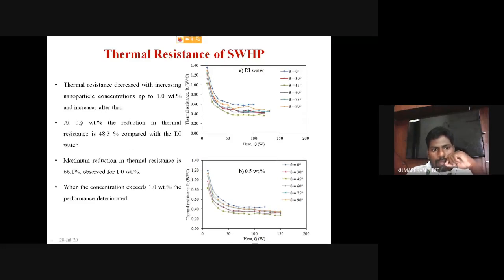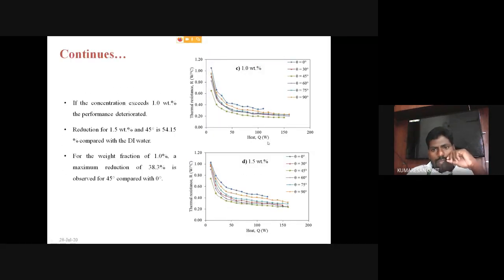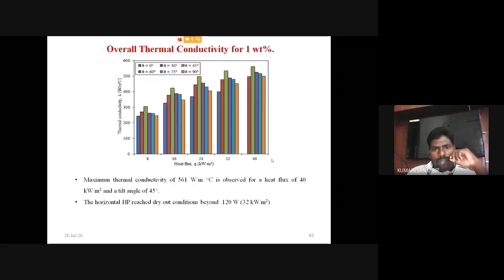So you see here, for a 0.5 weight percentage, the reduction in thermal resistance is about 48.3% compared with the DI water, and the maximum reduction in thermal resistance, about 66.1%, is observed for the 1 weight percentage of the nanofluid. And this continues for the 1.5 weight percentage.